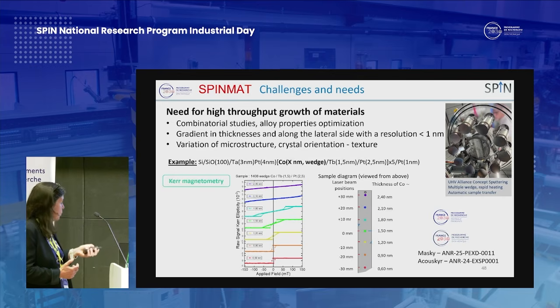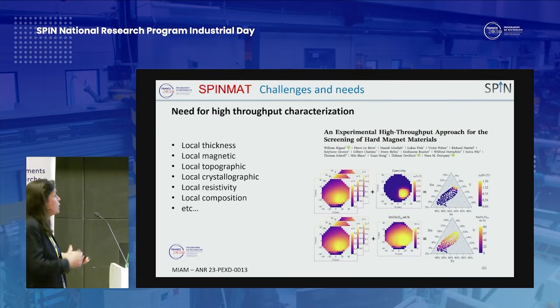Here is an example where you can see the study of the effect of cobalt thickness on the magnetic property within a single stack with a well-mastered cobalt wedge. And this study shows also that we need some high throughput characterization, for example, to evaluate local thickness, magnetic property, but also topography, crystallographic phases, resistivity, composition, and so on. And the last example shows this screening of hard magnets through a high throughput approach, combining high throughput growth, and also fabrication, characterization, and analysis.